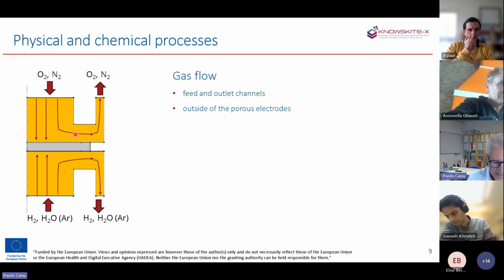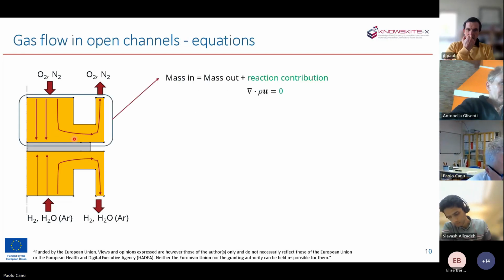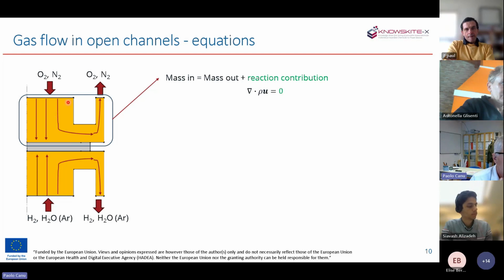The flow outside of the electrode is quantitatively described by a few equations. The first one is the conservation of mass, which means that the total mass entering from this side and leaving from the other side must be combined with the velocity, so that if we are losing some mass, then the velocity will change. But what is important is that there's no reaction in the yellow area, where the yellow area does not include the electrode, just the empty channel.